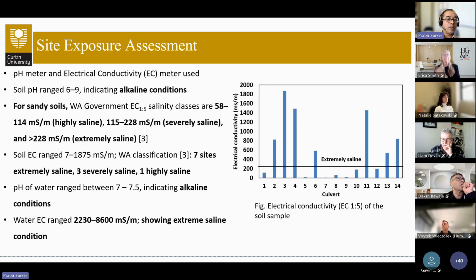pH of the water ranged between 7 and 7.5, indicating alkaline condition as well. Water collected from the site was tested for electrical conductivity, which ranged from 2,230 to 8,600 millisiemens per meter, showing again extreme saline condition. So both soil and water tests indicated extremely high salinity in almost half of the sites we inspected.